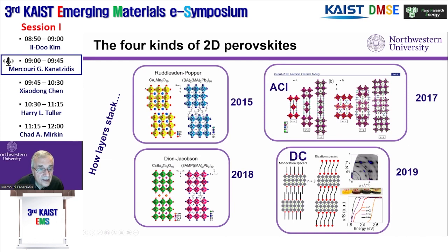And you see here an oxide perovskite in yellow, and you see this layer is shifted over this layer by 1/2 a unit cell. And the same happens in the other direction, 90 degrees. And this stacking defines the Ruddlesden-Popper motif, because there's this stacking down below here, where you see in the oxide, they're not shifted. They're directly one on top of the other with this cation. And this stacking defines them as Dion-Jacobson.